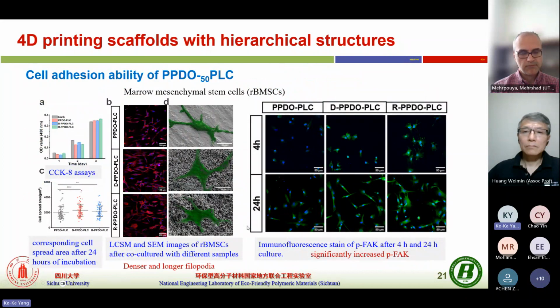At last, we also evaluated the cell adhesion ability of these copolymers, and we find compared with the material with a smooth surface, the rough surface can show much better cell adhesion, with denser and longer filopodia on the surface, and the cell attachment area is also increased compared to the control group.